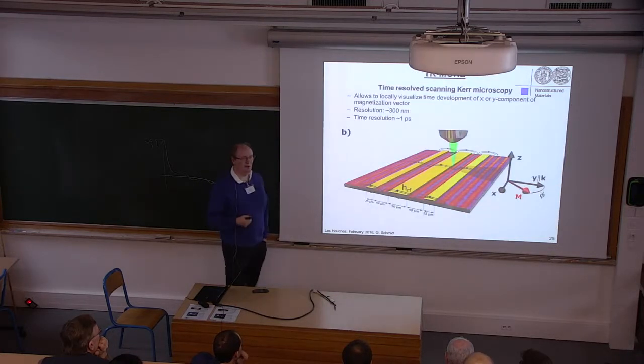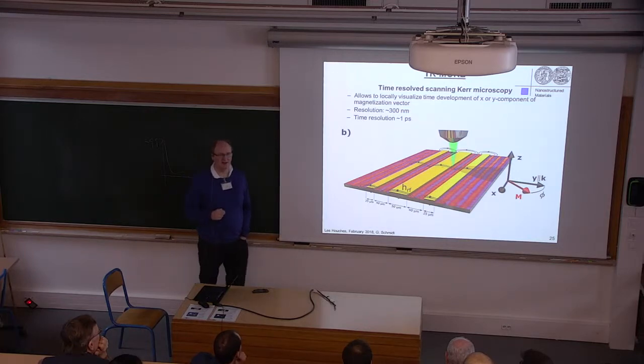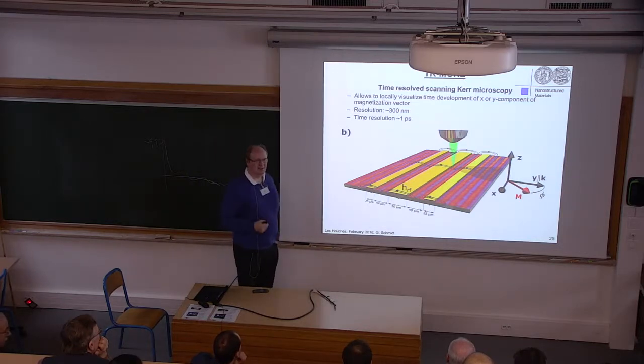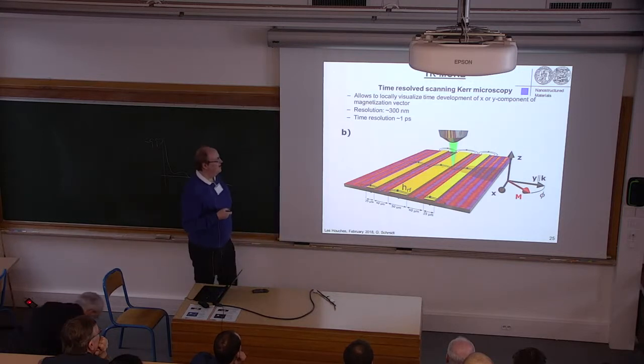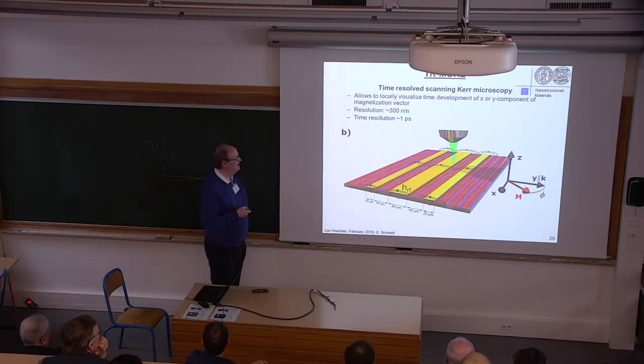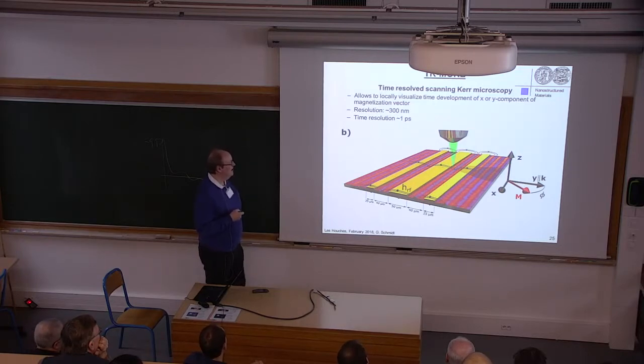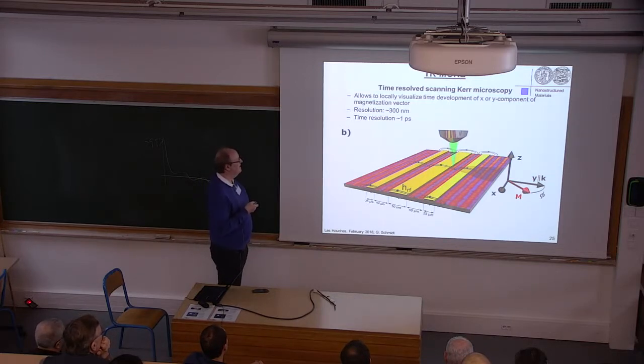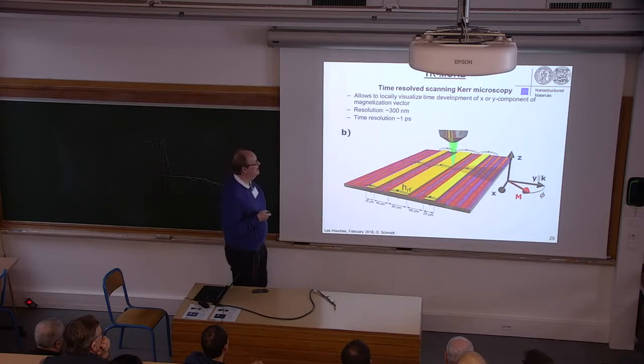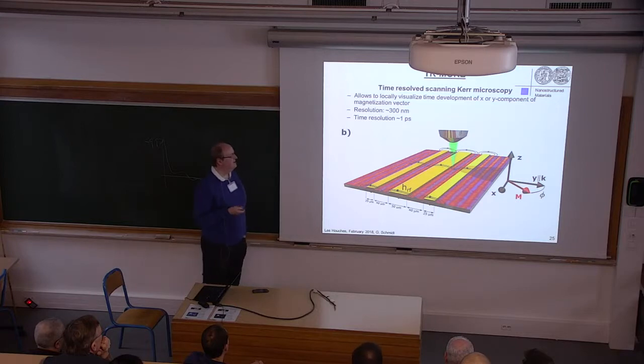And then came Georg Woltersdorf and he said, hey, I can do better than you. No, he didn't say this, but he said, I can do a very nice experiment, because he does scanning time-resolved Kerr microscopy. So basically, he can scan with a resolution of 300 nanometers and measure FMR with a time resolution of 1 picosecond. And this allows us to locally visualize the time development of the X or the Y component of the magnetization vector.